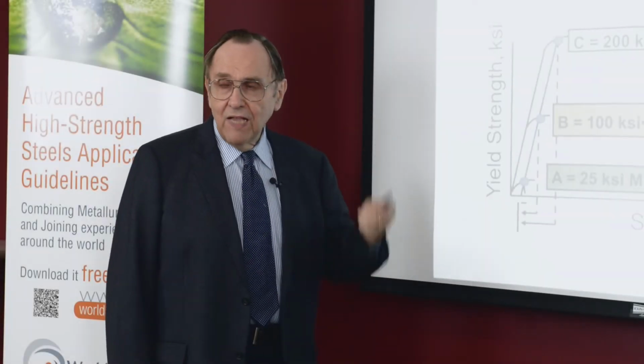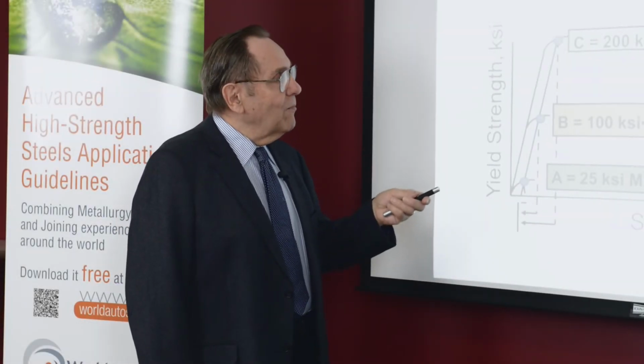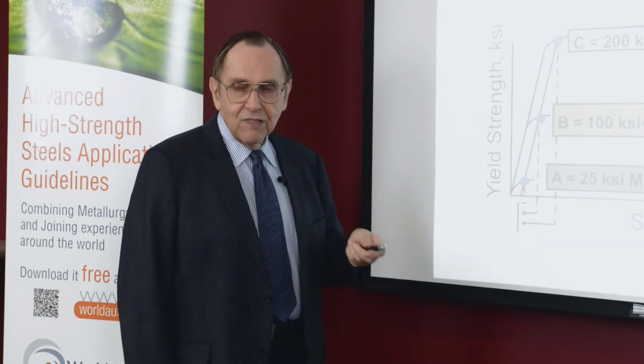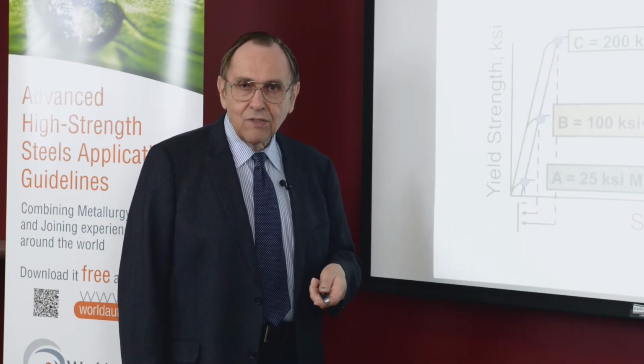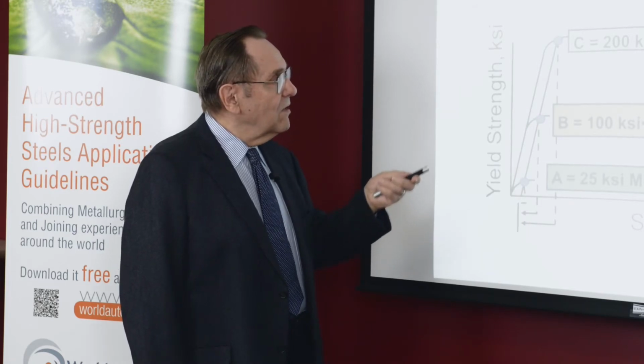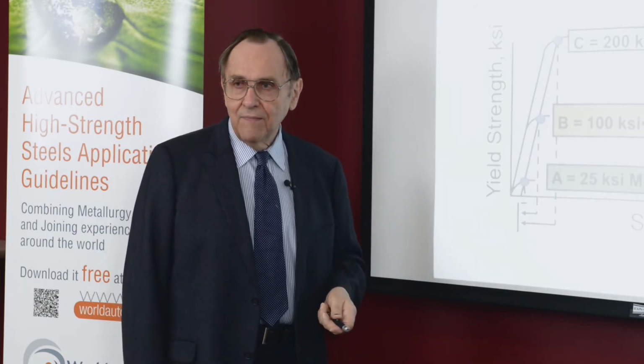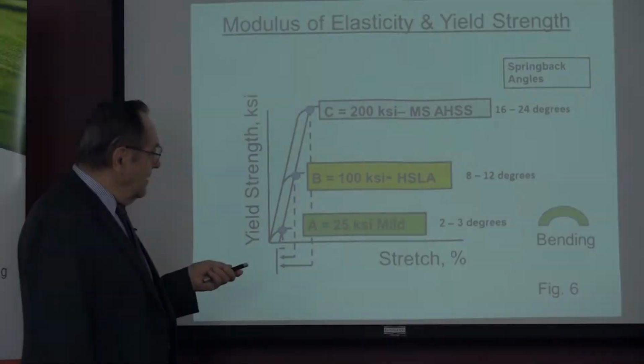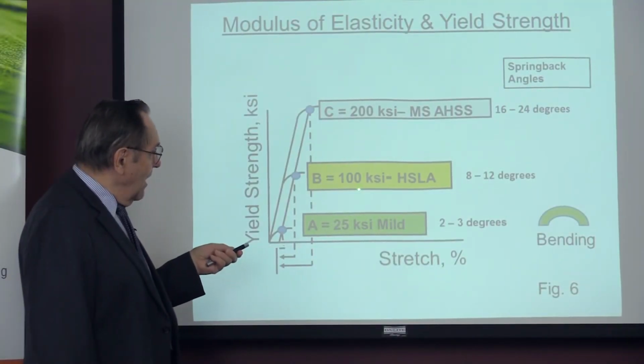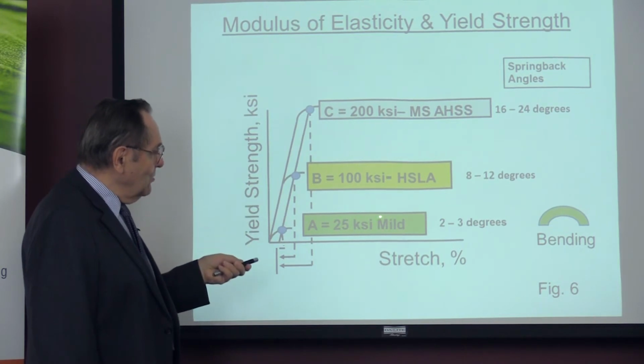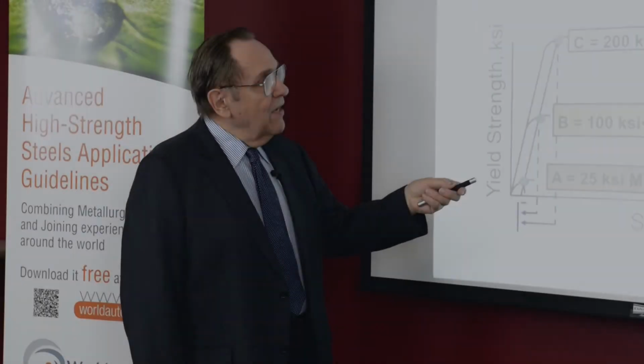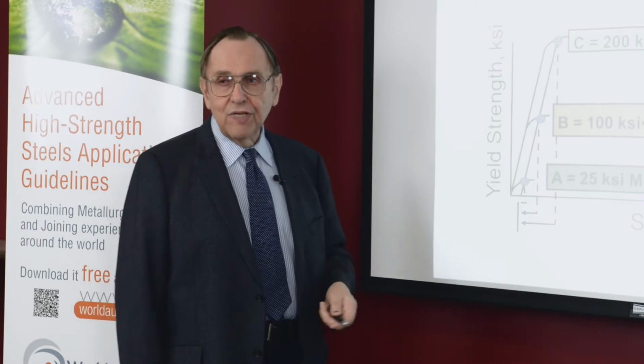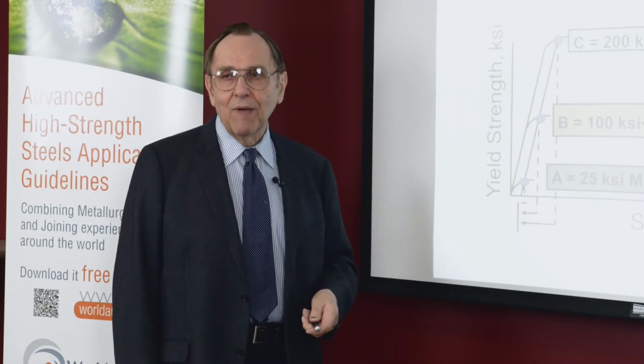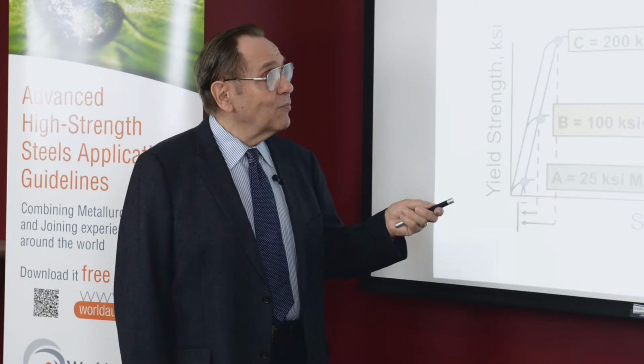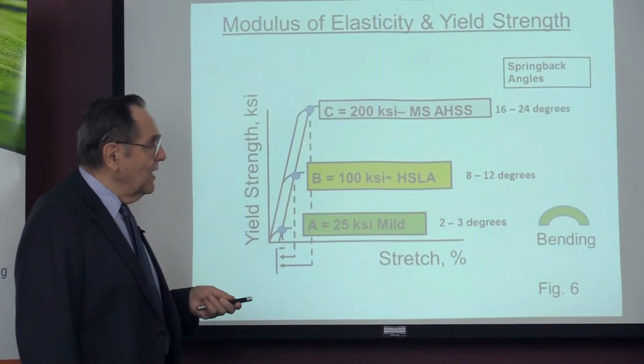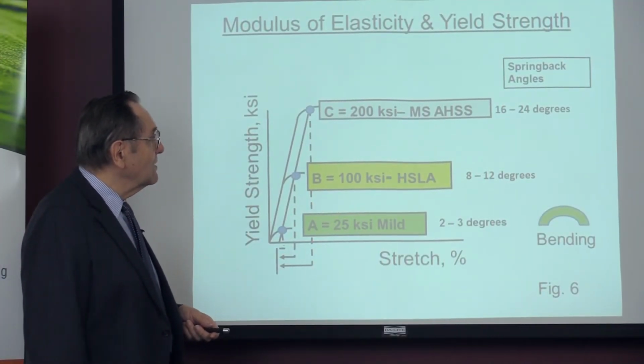Now comes the advanced high-strength steels, which number 1 is the martensite, the martensitic steels, which in this case has a yield strength of 200 KSI. Very, very strong. And now this is 8 times what you would find with a mild steel, and you're having 16 to 24 degrees of potential bending and springback. And that is a tremendous problem that you have in creating a stamping to specification.